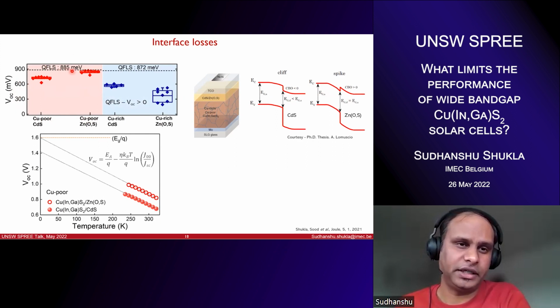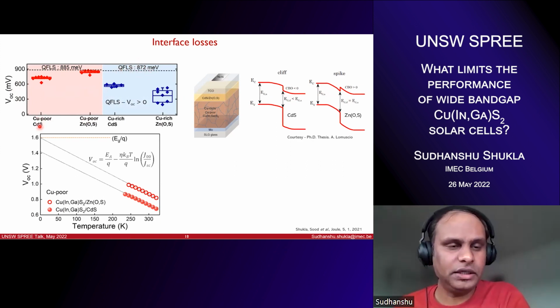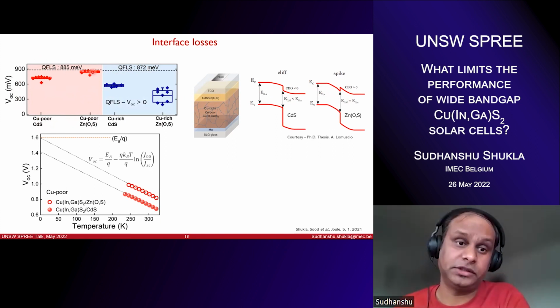And here you see the copper-poor absorbers on the left, which had a quasi-Fermi level splitting of 865. Copper-rich has a quasi-Fermi level splitting of 872, pretty much similar. What you see here is that when you replace cadmium sulfide with zinc oxysulfide, your VOCs become as close as the quasi-Fermi level splitting, which is very good.